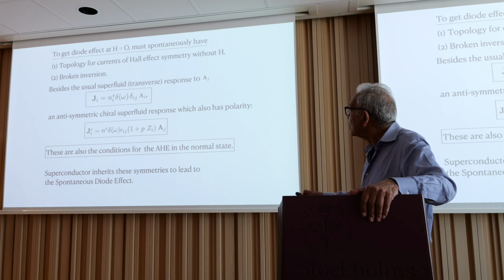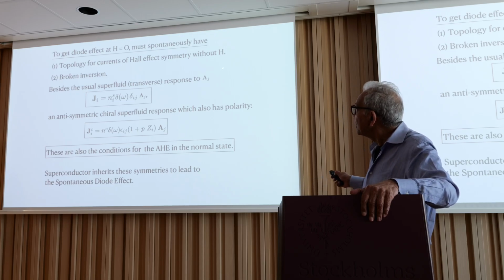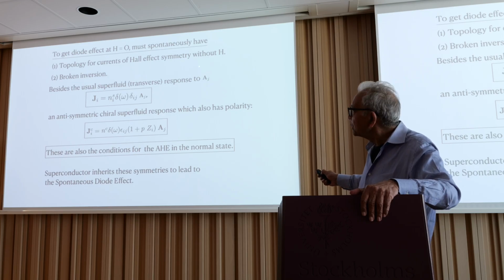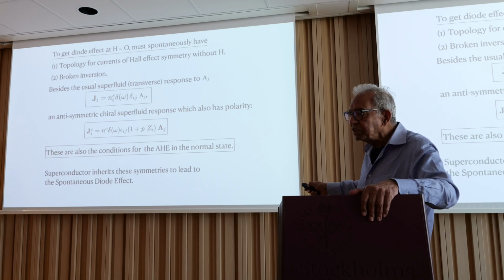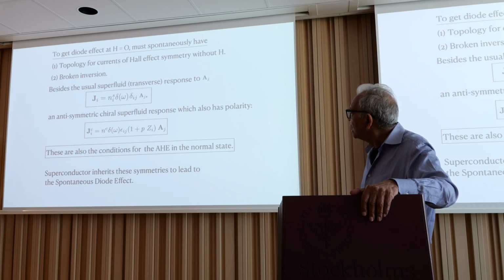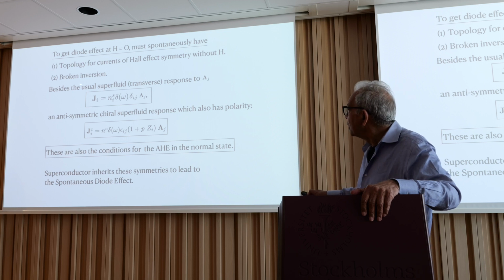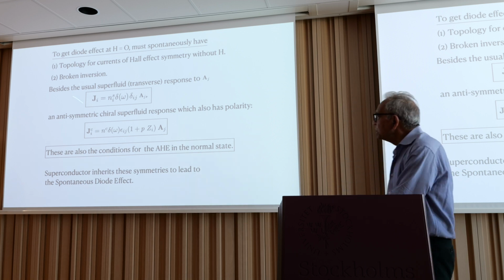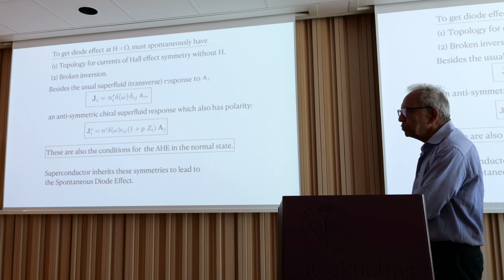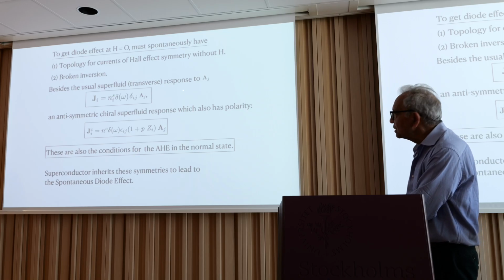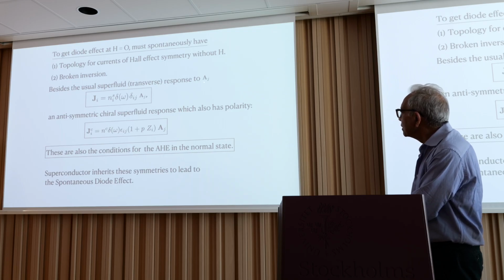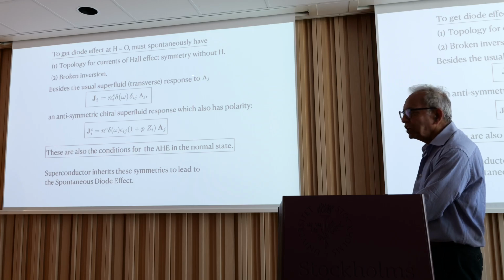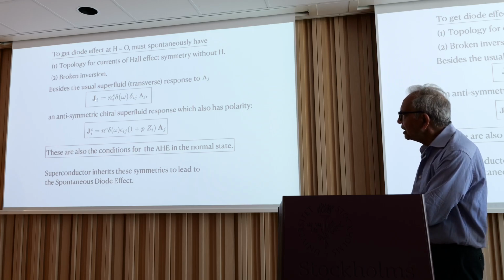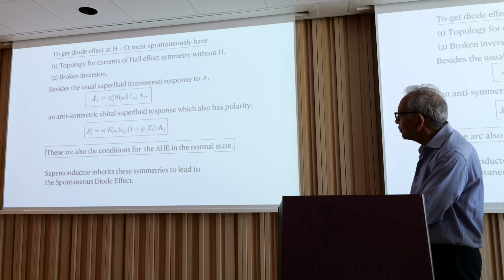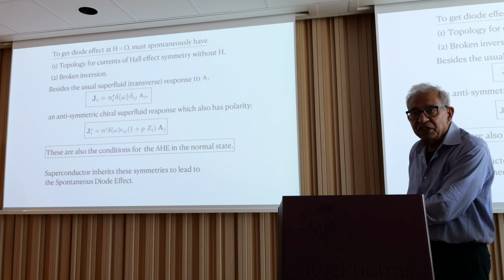We should have topology of currents with Hall effect symmetry without applying magnetic fields. We should have broken inversion, and these two remarks can be put in the form of a simple equation, which is that besides the usual superfluid response to a vector potential, and if I, for ease of writing, take this vector potential to be in the transverse gauge, then there's a current at zero frequency which follows the principal axis of the crystal.